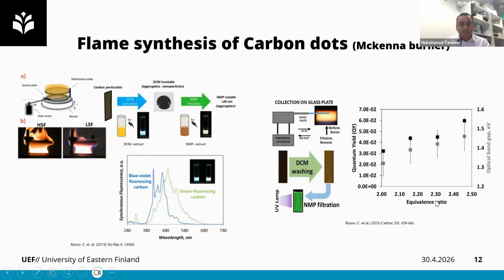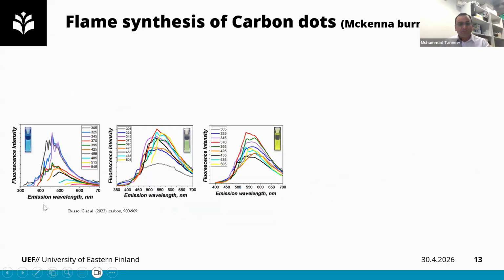And then they have studied the origin of photoluminescence, so why it is happening in these nanostructures. They have observed that the blue dots are basically small PAHs, like polyaromatic hydrocarbons, trapped inside the particles, which are active by UV light because they are quite small and they have a very large band gap. So they need quite high energy to be active. So they are considered as UV blue dots.